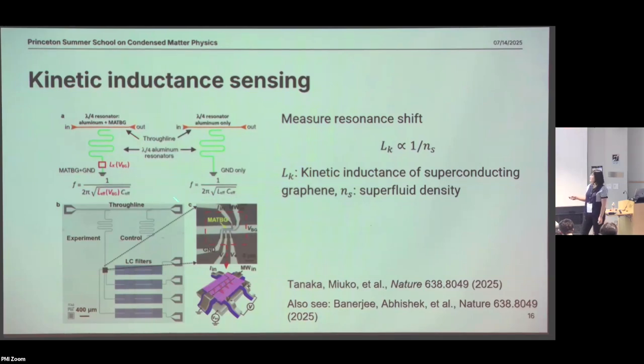And because of that, the total inductance is changed. So now the total inductance has not only the part coming from the aluminum resonators, but also the part coming from the MATBG. They can also tune the gate voltage of the MATBG to get to different states and see how this effective inductance changes. By measuring the resonance shift, we know the inductance. Because the inductance is proportional to 1/the superfluid density, one can directly get the information about the superfluid density. That's the idea, but with higher resolution, and this is the type of scheme that's needed when your sample is only on the micron size and with nanometer thickness.